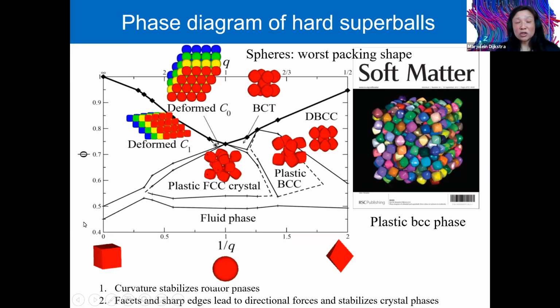On the y-axis, we show the packing fraction, and then on the x-axis is the shape parameter. So it goes from cubes via spheres down to octahedra. For very low packing fraction, we find a disordered fluid phase. And then if we increase the packing fraction, it can form a plastic FCC crystal phase or a plastic BCC phase. These plastic crystal phases are just the FCC or the BCC phase, but the particles can rotate freely while sitting on these lattice positions.